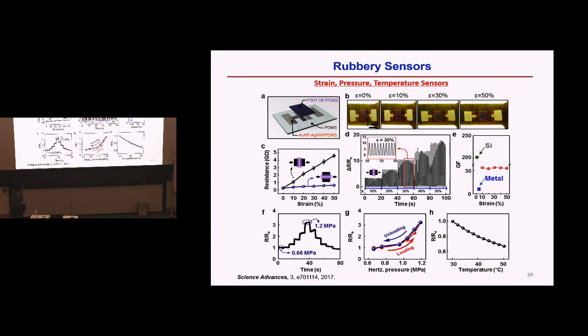The most accessible strain sensor is based on the metal strain gauge. The metal strain gauge has an operation zone of 5% because of the elastic zone of these metals, but the gauge factor is in the range of 2 to 5. So you slightly increase the operation zone, but your gauge factor sensitivity is much lower.